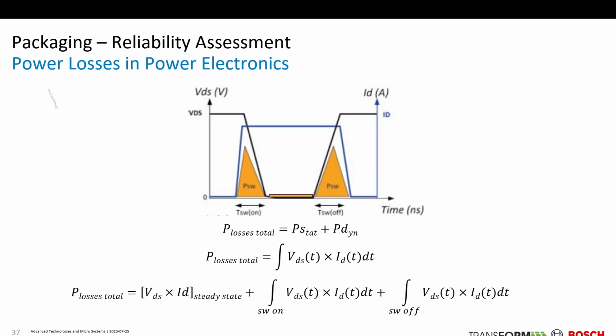Where does the loading come from? We have the situation of power losses during the switching events in your power electronic systems. This means we have the steady state situation. This is more or less given by the RDS on value of your power semiconductor. But you have this switching event at the beginning, switching on, and at the end the switching off situation. And the power losses in total are given by the integral of the curve here during the switching event.